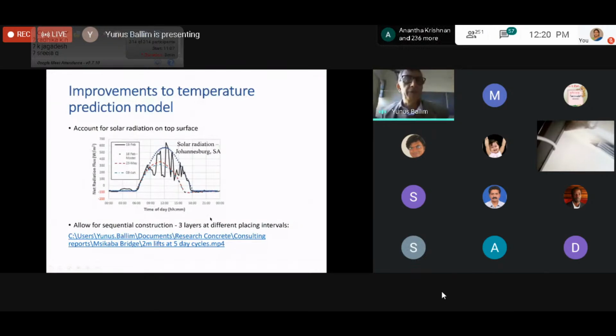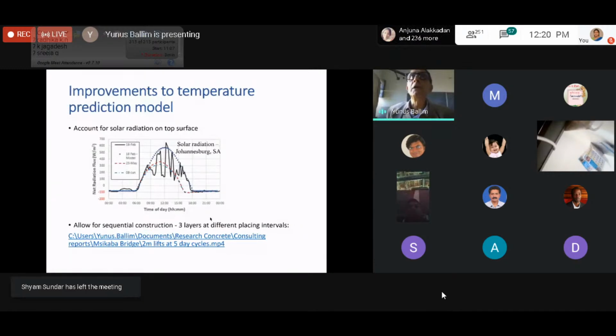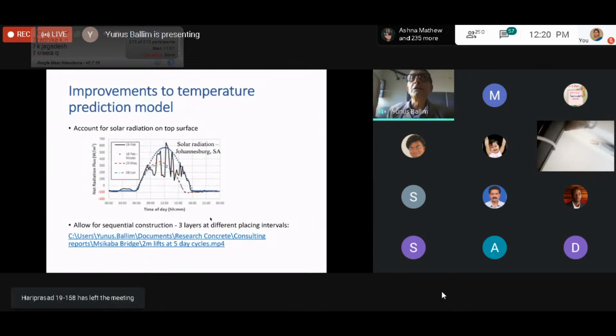Which is, you know, when people build dams or bridges or large foundations, you generally do not cast in one layer. And so the concrete is placed in sequential layers, mainly to allow the heat from the lower layer to dissipate. The problem is that depending on the time intervals of your casting sequence, when you place another layer of concrete on top of a previous layer that has not yet gone through its full heat liberation, you are now creating a situation where you're pushing heat from a lower layer upwards into the subsequent layer. And so it goes as you cast sequential layers.